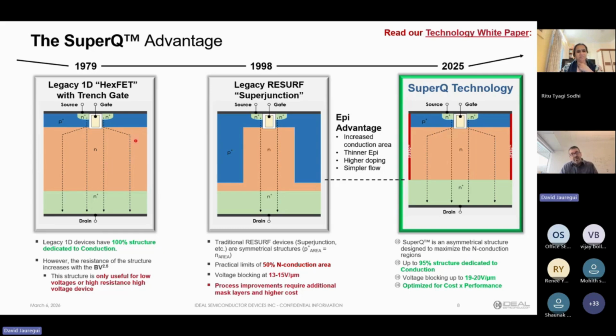And so a lot of those one-dimensional limit lines you see on paper about silicon, and why it was time to reinvest, are based on these structures. And then when Infineon came out with superjunction, which is really what they call a RESURF structure, a reduced surface field structure, at the core, what they're doing is carving out half the silicon and putting these P plus pillars. And what these P plus pillars do is they charge compensate this N drift region.